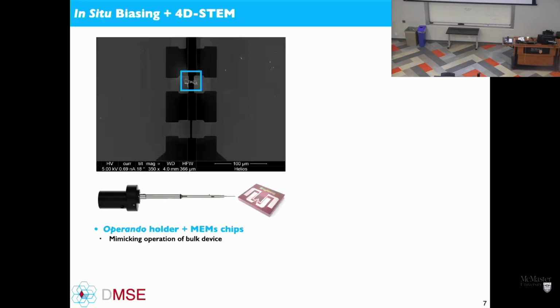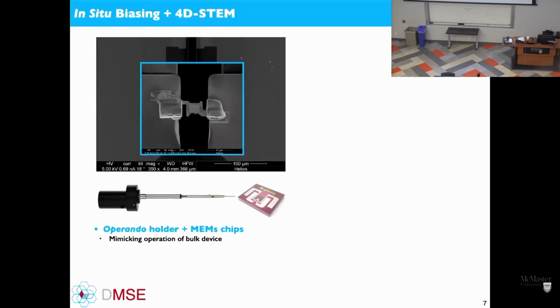What I do have in my backyard is an electron microscope, and that electron microscope, paired with FIB, and with the latest advances in FIB, we're able to make these mini capacitor structures from those thin film capacitor structures grown on an actual device. So what we can do is FIB out and cut out that sample and build our little anti-ferroelectric capacitor. There is platinum on either side, so our substrate is conductive in this case. Our top electrode is also platinum, so it's conductive.